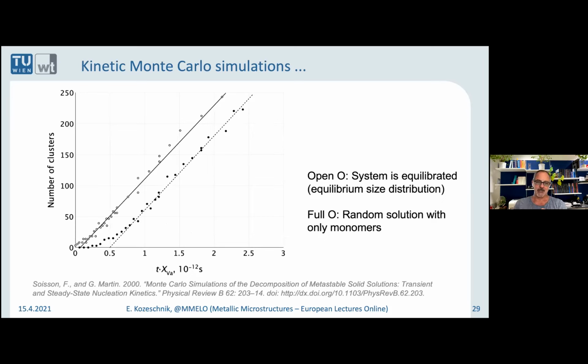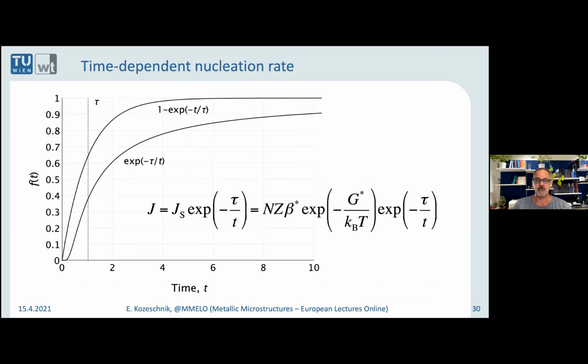François Soisson and Georges Martin made a very nice experiment on the computer where they annealed a system at high temperature and then quenched into the precipitation range, or started with a distribution very close to the phase boundary. You can see the open circles are the number of clusters for the equilibrated system, and the full circles show a clear time lag until steady state is reached. The references are given if you want to know more about that. So transient nucleation does exist, and you can formulate that in mathematical terms with either of these two functions, 1 minus exponent or the exponent of minus.